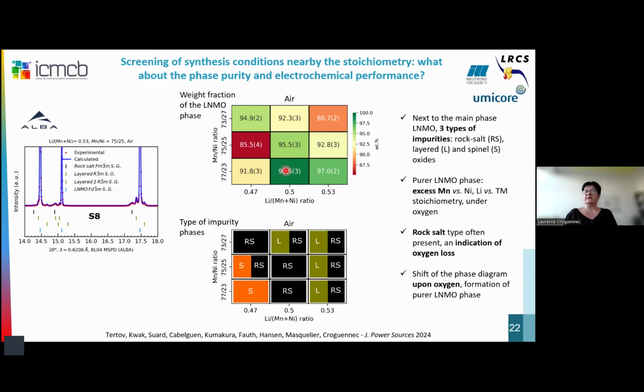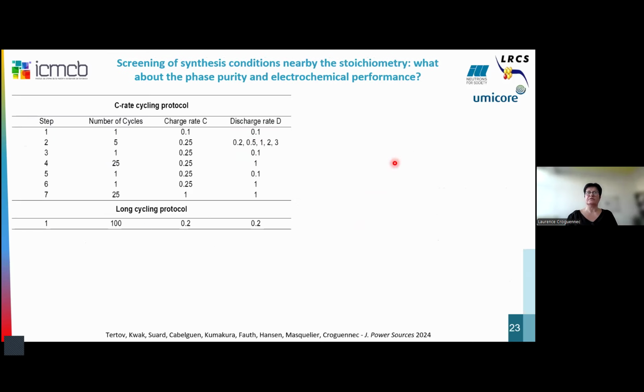So you can see that depending on the conditions, we can really have highly impure materials, such as this one, with different natures of impurity, as you can see here: spinel, rock salt. And for this one, for instance, we have layered and rock salt. For this blue one, the manganese excess, stoichiometric in lithium, we have the presence of a tiny amount of rock salt impurity. So you can see that we have three types of impurity in that kind of materials.